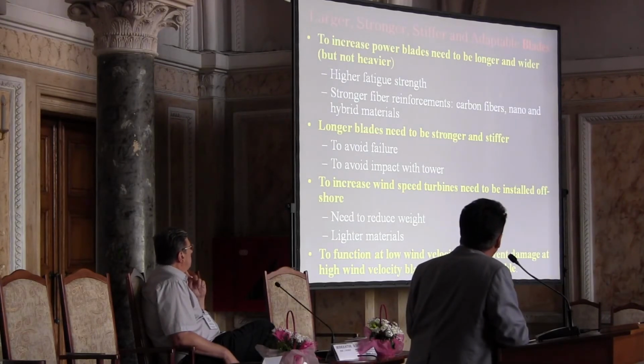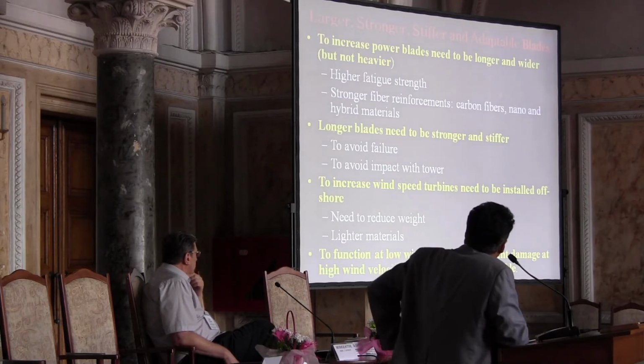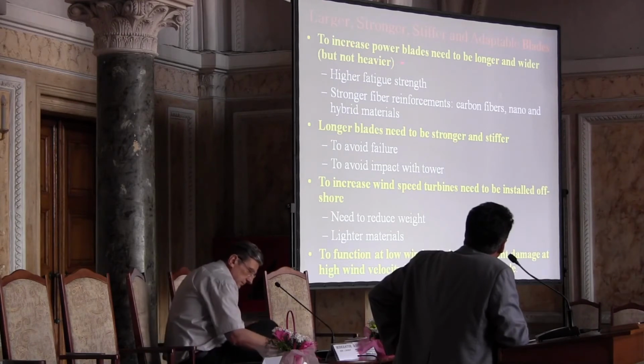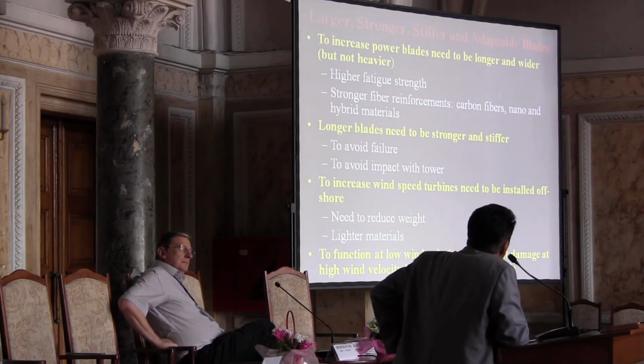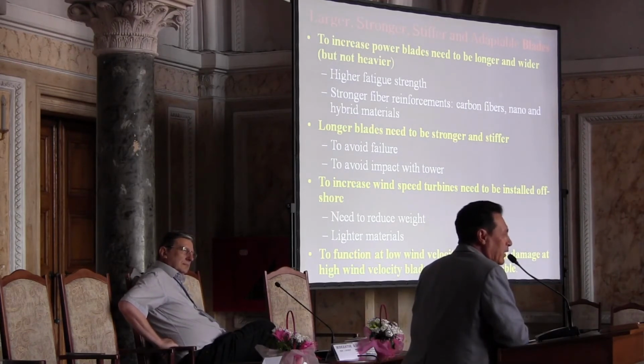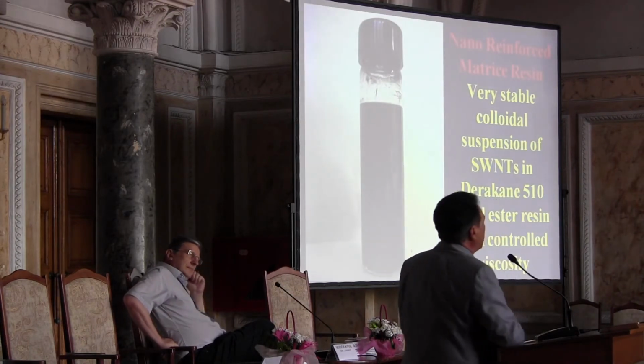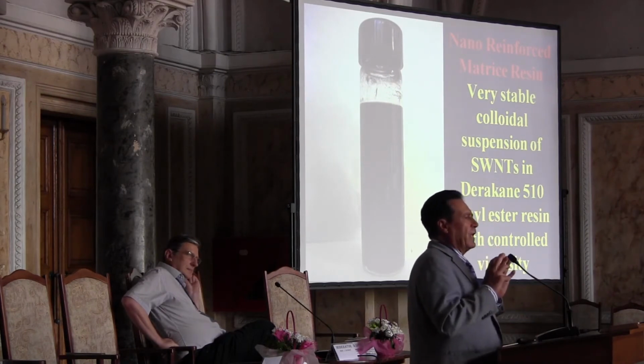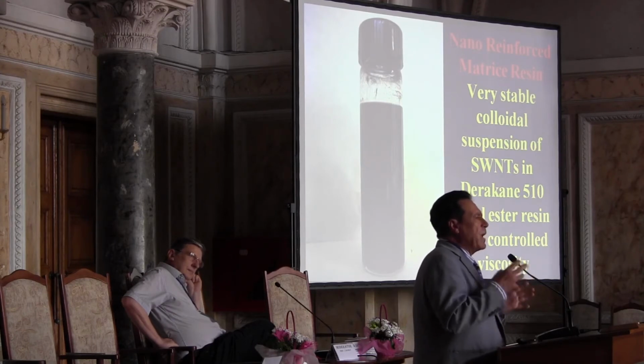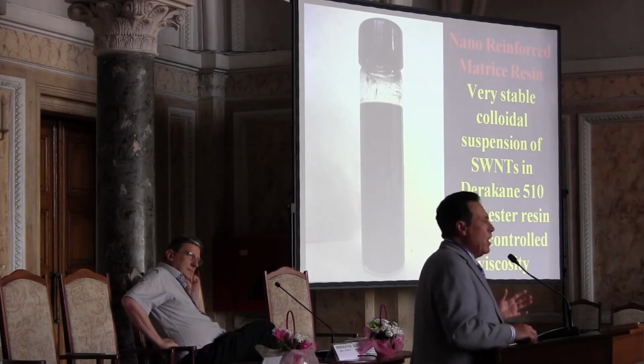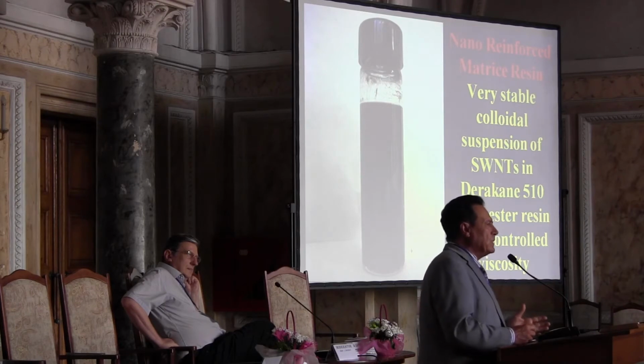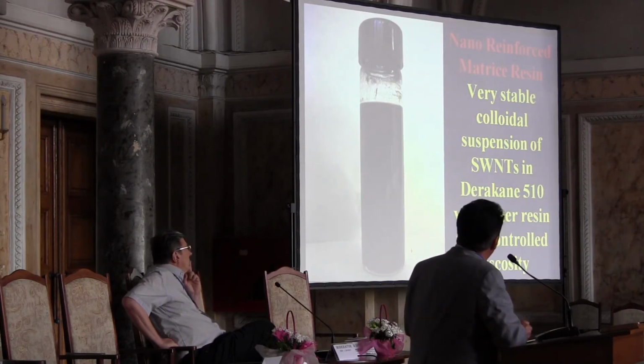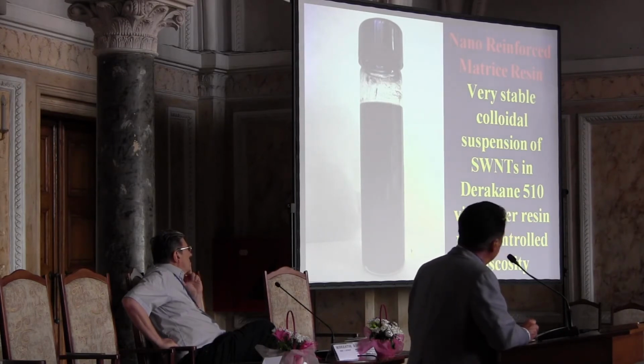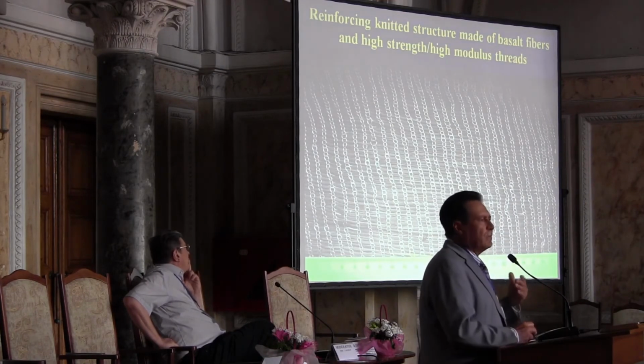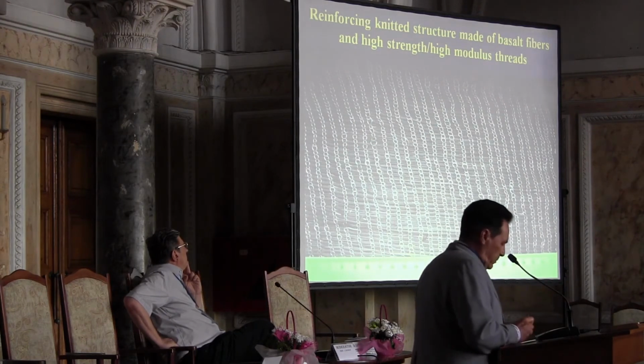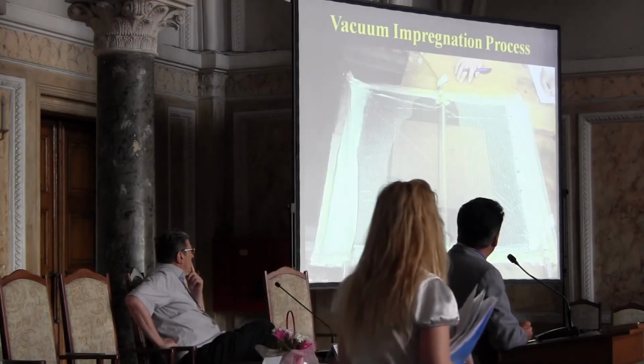I don't have time to go through all of this, but these are some of the typical challenges that you are facing. So we need larger, stronger, stiffer, and adaptable blades that are still able to be fabricated in an economic way. That means that you have to control not only the reinforcement, but also the matrix. So instead of having a resin, you now have a fully integrated carbon nanotube system in this resin. In this particular case, you are dealing with the Derakane 510, and we can use other reinforcers, not only glass fiber, but also basalt fiber. We can have these hybrid reinforcements, and then